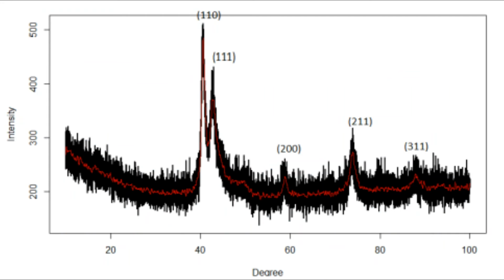To determine if the high energy mechanical milling had formed a high entropy alloy, the milled powders were analysed through XRD analysis. The produced XRD spectrum would have the peaks indexed to determine what phases were present in the sample. For the formation of a high entropy alloy, there would ideally be a single phase that had formed. This desired phase would be an FCC phase, as this phase has been found to be the best for catalysts to facilitate a hydrogen evolution reaction.